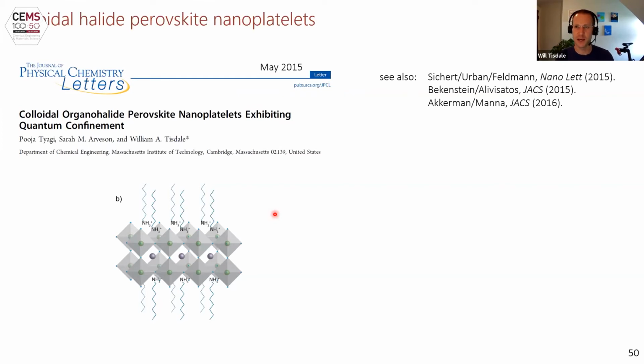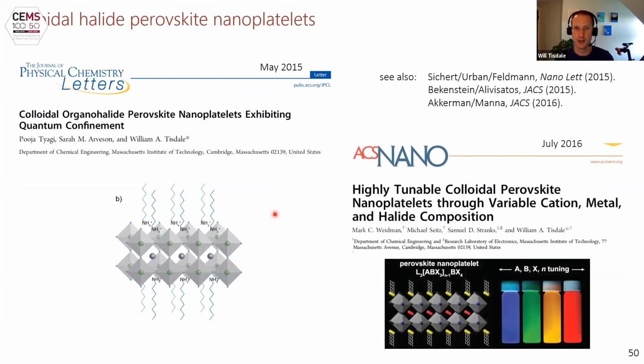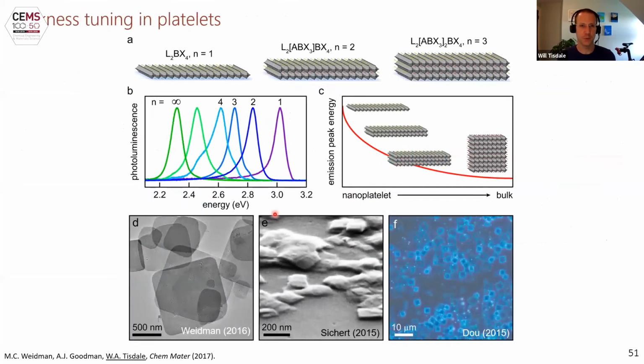At the same time we did that, a number of other groups were also working on two-dimensional versions of colloidal perovskite nanocrystals. We eventually got good at making these materials intentionally and published a follow-up paper with a systematic study. We label these materials by the number N, which refers to the number of octahedral layers in thickness that the material is. So N equals 1 has 1 lead halide octahedra, N equals 2 has 2 lead halide octahedra, N equals 3 has 3.